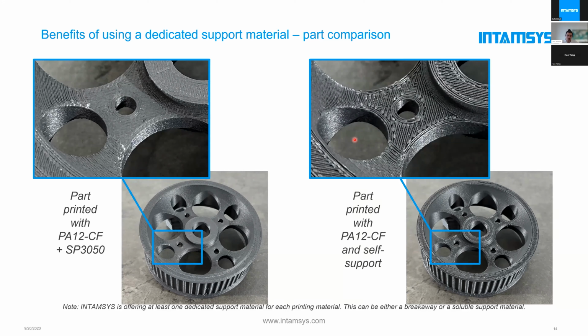If we compare the self-support here, we see the lines look like an under-extrusion effect, because you have no bottom layer, no support interface where you squeeze your lines. They get half printed in the air, and therefore it's a little bit weak. And what can happen sometimes, because here it just looks not that good, but it's all right, the part, let's say. But what I found on the first layer of the part, where it had contact to the raft, I even ripped off some lines. Yeah, so I just peeled off the raft, and not too hard, but let's say to make it time effective. And then you can even damage those lines.